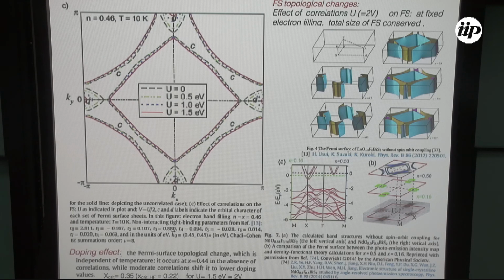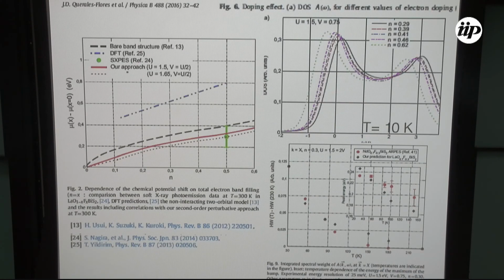Well, okay, so here I want to just show that we obtain results for the Fermi surface, where you see that if you have the uncorrelated band, you have this, and when you start including the effects of correlations, you increase the nesting. So that's also some of the kind of approaches some other people were proposing were relevant in these materials.